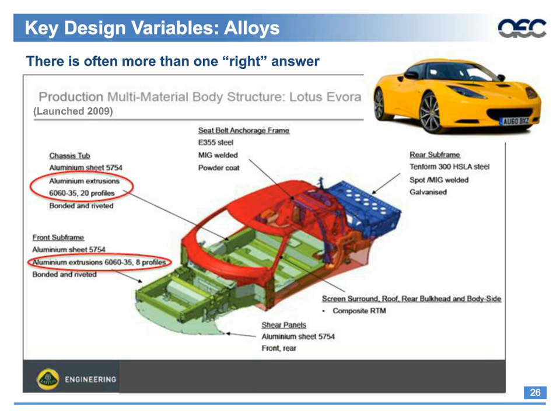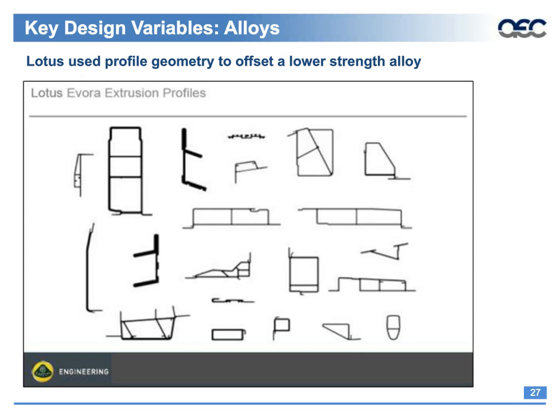But when you actually look at the variety of extrusions that were designed into this, and remember, these extrusions may cost $500, $1,000, $3,000 to tool, depending on the size. These are all the different geometries, different profiles that were used in the Lotus Evora. They use some lower strength alloys, but they design specific profiles because the tooling cost is so low that they can specialize the part to exactly what they want. And you can see how there's material put where you need it for either fastening or for strengthening needs. So you don't need to create simple bars and T's and rods and things. You can create exactly the shape that you need to meet the design needs.